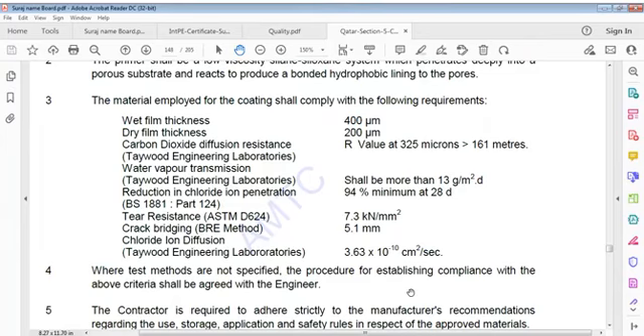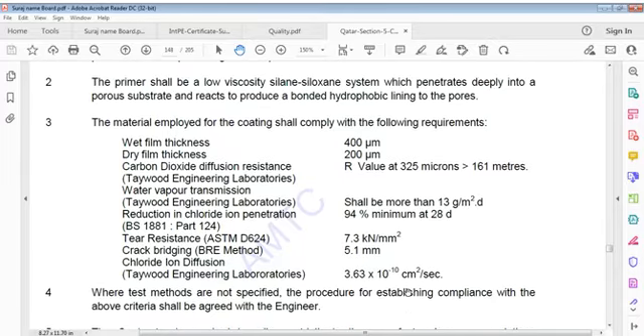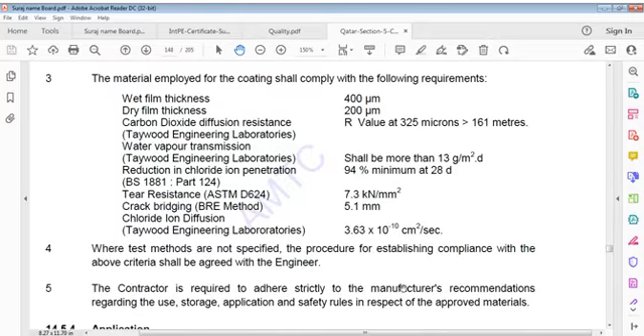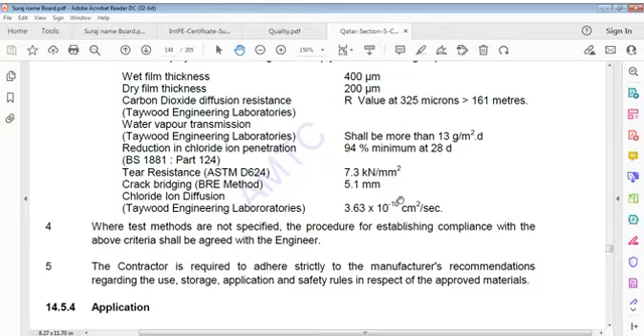Therefore, carbon dioxide diffusion resistance is R value 325 microns, and water vapor transmission shall be more than 13 grams per square meter. Reduction in chloride ion penetration is 94% minimum at 28 days, because this membrane shall not allow chloride penetration once the coating is done. So that's where the 94% reduction is. Only 6% penetration is permissible in this case, which is of course not that detrimental for the long-term requirement. And tear resistance is 7.3 kilonewton per square millimeter, and crack bridging is 5.1 mm.